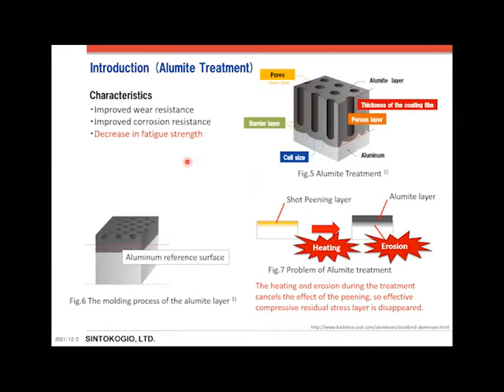The next method to improve wear resistance is alumite treatment. The characteristics of the alumite treatment include improved wear resistance, improved corrosion resistance, and decreased fatigue strength. The structure of an alumite layer is shown in figure 5. The problem here is a decrease in fatigue strength. This figure 6 shows the alumite formation process. Alumite not only forms on the surface of the aluminum alloy, but also grows into the inside of the aluminum alloy.